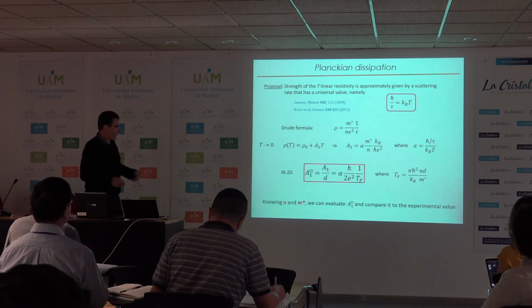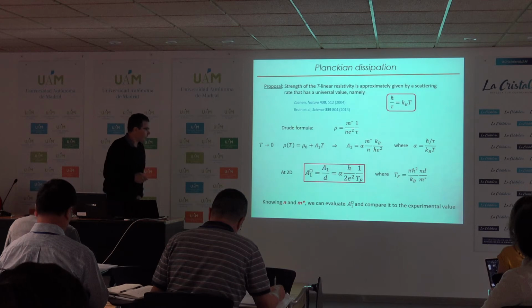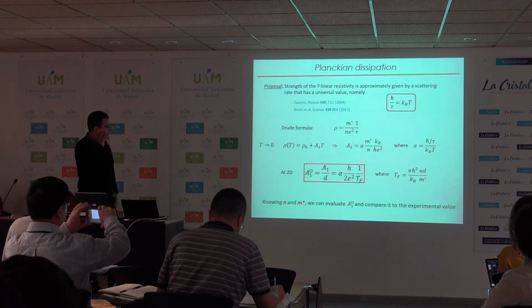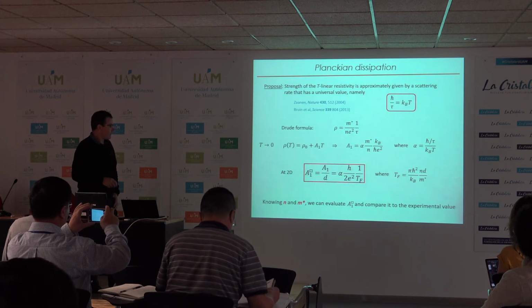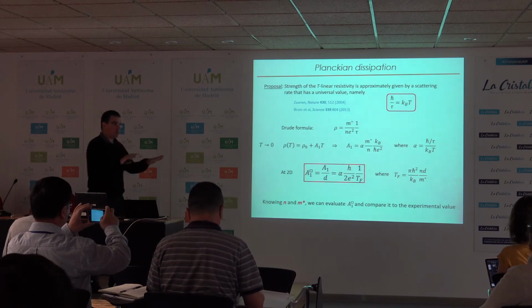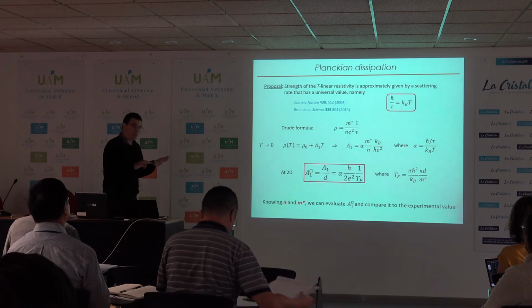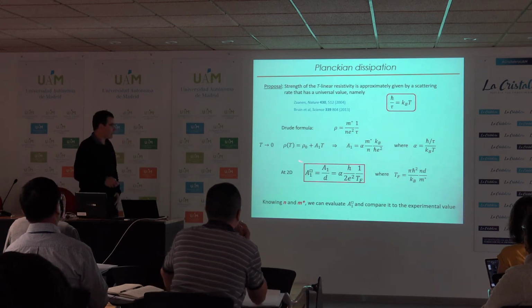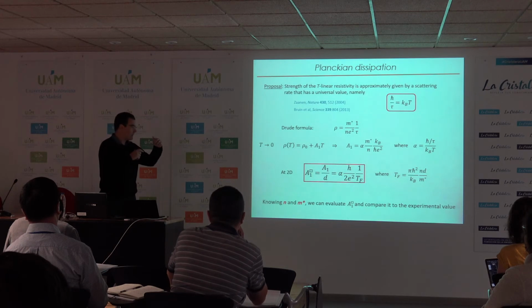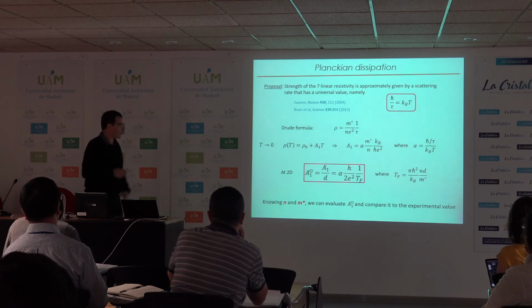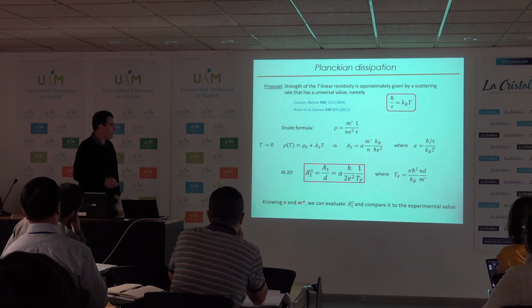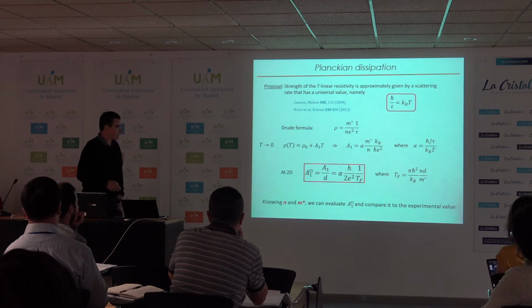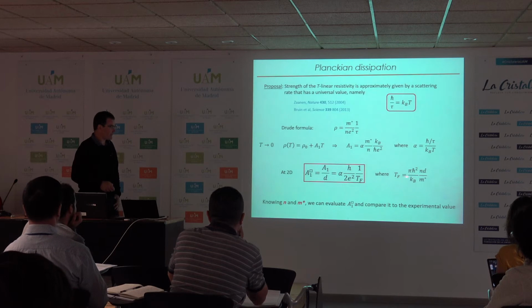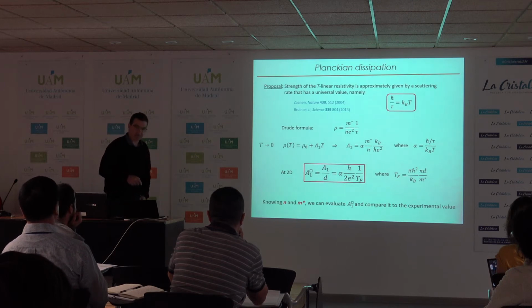And what we have done is that we have compiled a lot of these numbers in terms of the coefficient per square to basically compare different families of cuprates. So this is just A1 divided by the c-axis, so the distance between copper oxygen planes, to normalize the number. And basically, this coefficient is inversely proportional to the Fermi temperature, which is basically given by the ratio of the density of carriers divided by the effective mass.